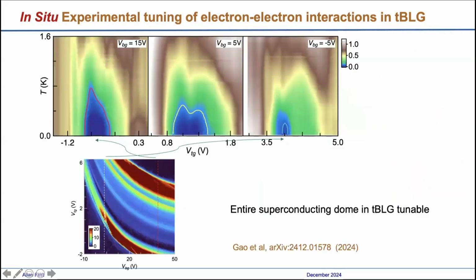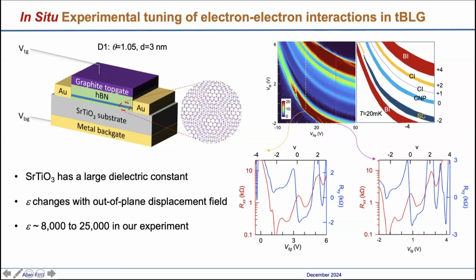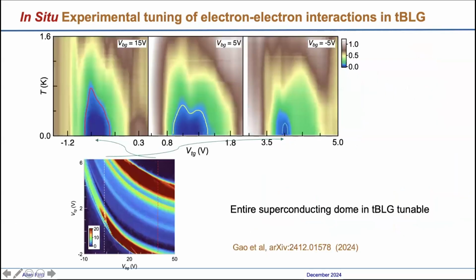Now what we'll do is stay at one back gate voltage and sweep the top gate, which changes the charge density, so we can go through the superconducting, correlated insulating and band insulating states at each different dielectric constant. So this is what we did. For example, at a back gate voltage of 15 volts we see a superconducting phase, and at -5 volts this is also a superconducting phase. Here we're outlining a superconducting dome. This shows the entire superconducting dome is tunable depending on the dielectric constant.